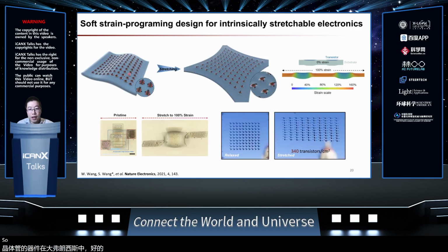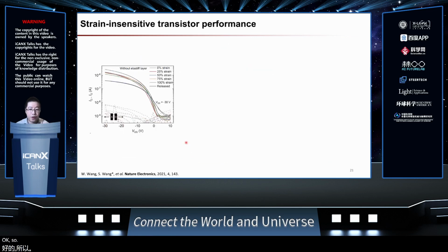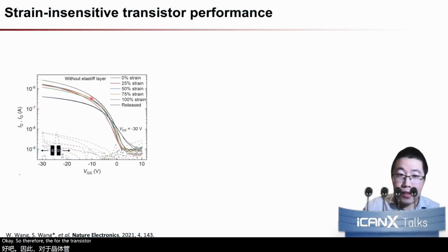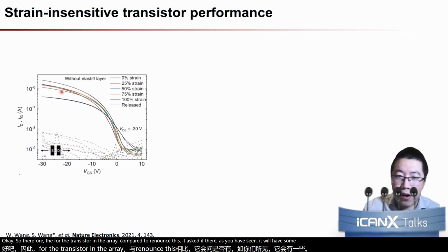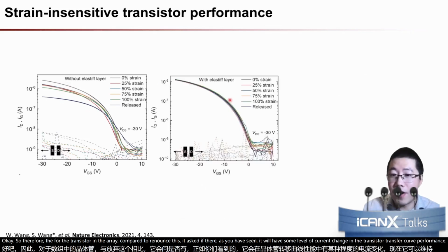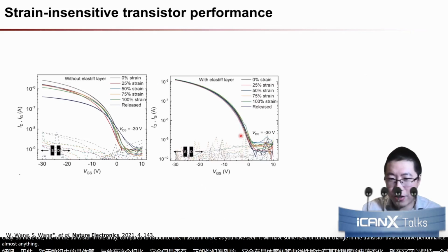So after combining this design, we can see that in this transistor array, which still has the same integration density, when the entire array is deformed to 100%, the actual strain applied on the transistor is only about 15%, much less. Therefore, for the transistors in the array, compared to without this elastic layer, where as you have seen there is some level of current change in the transistor transfer curve, now it can maintain a very stable performance with almost no change in the current level.